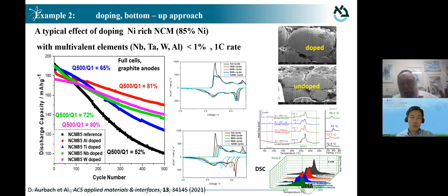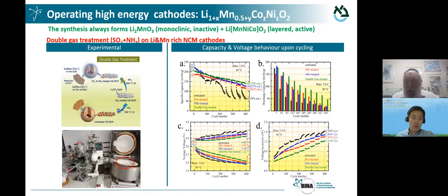But I want to go further with the screening here, and the next story relates to very interesting material, which is the lithium and manganese rich. So we have the same five elements, but now we change the stoichiometry. With lithium we have more than one, with manganese we have more than 0.5, and oxygen is 2, and then the rest is distributed between cobalt and nickel.